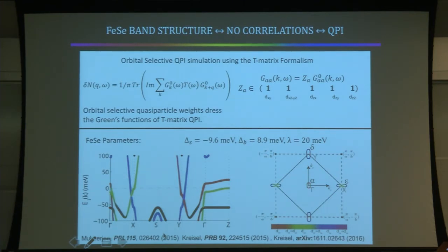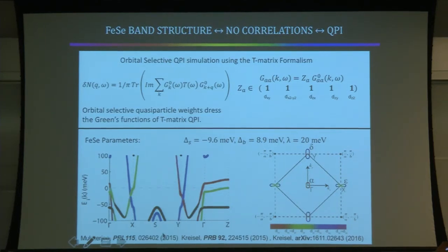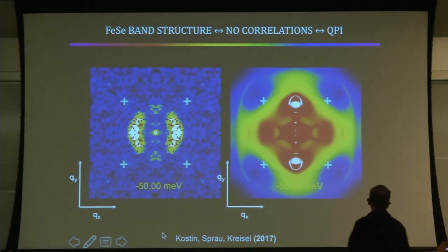Okay, now let's look at our band structure. A fully coherent band structure. You just set the quasiparticle weight for each Green's function to be 1 for every orbital and calculate what should happen in Friedel oscillations, in the normal state. So that's what we have here. Fully coherent 5-band Friedel calculation.